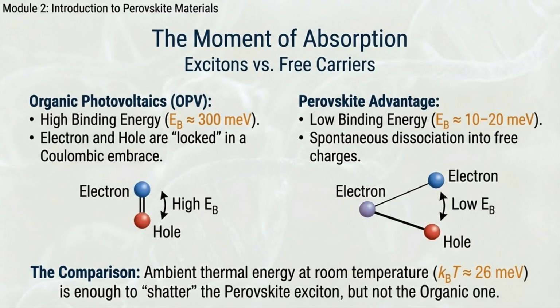Because the 26 millielectron volts of room temperature heat is greater than the 15 millielectron volt binding energy, the perovskite exciton is literally shattered by ambient heat within femtoseconds of its creation. The material spontaneously generates free, highly mobile charge carriers entirely on its own, without needing complex internal interfaces. But why is this binding energy so magically low? The answer lies in dielectric physics.